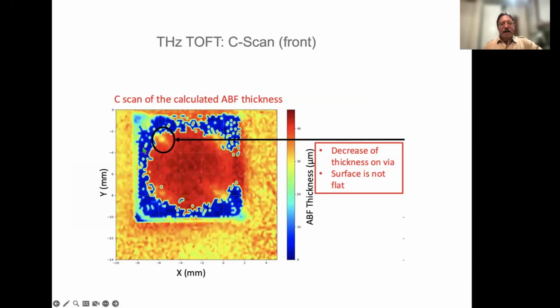Okay, so here again, this is a Terahertz C-scan, but here we're basically mapping the information we extract for the thickness of the ABF. This is on the front side. The ABF thickness actually ranges here from about 10 microns up to about 30 something microns. So some of this is an artifact. However, some of this is real.